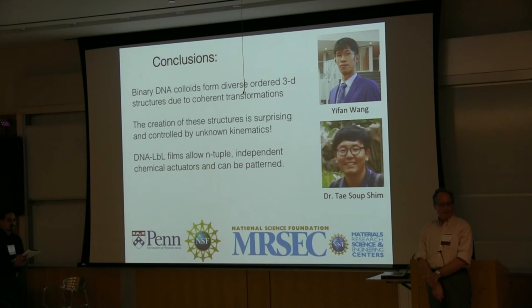We lost a lot of sleep over the shape of those fragments. And it turns out that the previous postdoc, not this guy, he was a chemist, so he was taught to always stir his samples before he dipped. And then there was debris, and he had little pinholes in his film. And then when it popped off the film, it got torn apart by the pinholes. And if you don't shake the sample before you dip, they come out very nice and uniform with no pinholes, and they pop off as large sheets. I don't know if that, does that make sense?